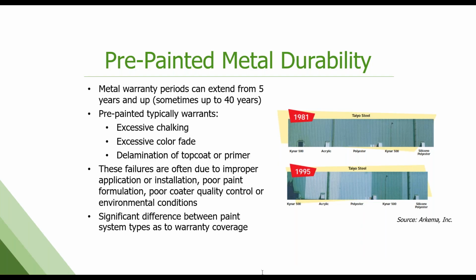So these warranties can be anywhere from 5 years and up to 40 years. There's some 50-year warranties out there. Pre-painted typically warrants for excessive chalking, which is that white fade that you get on buildings, excessive color fade, and then delamination of the top coat or the primer. Why a product might fail can vary a lot. It can be due to improper application. It can be an installation issue. It could be a bad paint formula. Maybe the coater didn't get the right amount of film on there for some reason. It could be environmental conditions that are outside of the warranty.